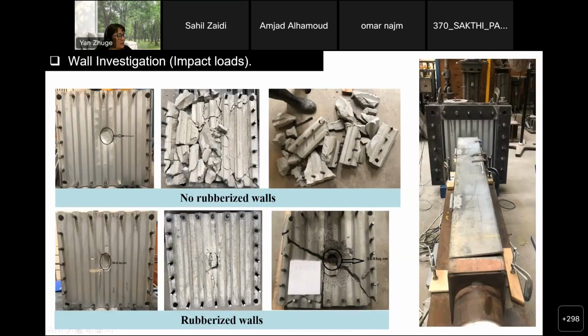And finally, we did some impact loading test. So that is normal composite walls for normal foam concrete. And this is composite walls with up to 17% of crumb rubber in the concrete. You can see under the impact load test, and this one, the inside concrete was just smashed into pieces from testing. However, after you have the rubber increase as crumb rubber foam concrete, for the same impact testing, although